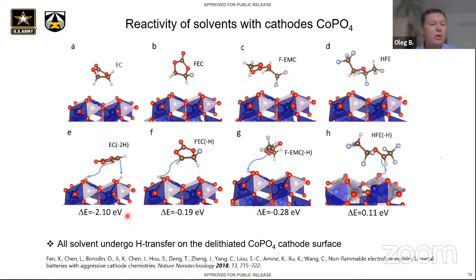That's very energetically favorable. In a real liquid electrolyte, probably it will not be able to move easily and get another proton because of packing restrictions. It might open up and evolve CO2, as I showed you in that case. But in this case, if it forms VC, it's also very easily oxidizable, right? As I've shown with very fast kinetics. Other solvents also had the same deprotonation reaction occurring. HFE was the only one which had a slightly positive energy, but with enough of the rearrangement fluctuation, and maybe including anions, that could be close to zero and would also deprotonate.